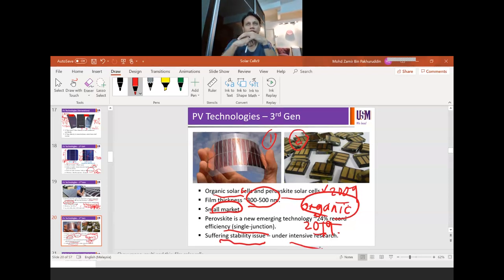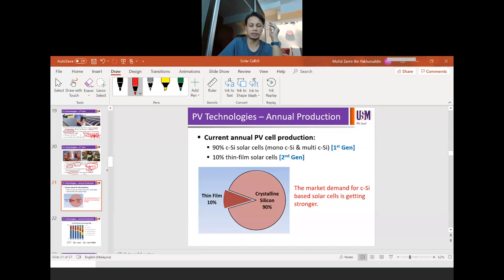In fact, if you manage to fabricate, for example, perovskite solar cells, say you do your FYP today on perovskite, and it's measuring around 15% efficiency, the next day you come into the lab, it might show only 2% efficiency. So this is due to degradation of the material within the solar cell. That's how serious the issue is. So it has a lot of potential, but quite a number of issues to address, particularly the stability problem.